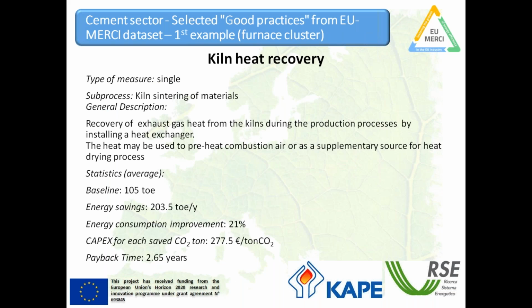This is a single measure, and it influences the process of kiln sintering of materials. In the situation before the intervention, the kiln using fossil fuels had no heat recovery system. A heat recovery heat exchanger was installed in the flue gas duct, and the heat was recovered. The heat may be recovered for preheating combustion air, which is pretty obvious, or it can be used as a heat source for other processes like the brick drying process.